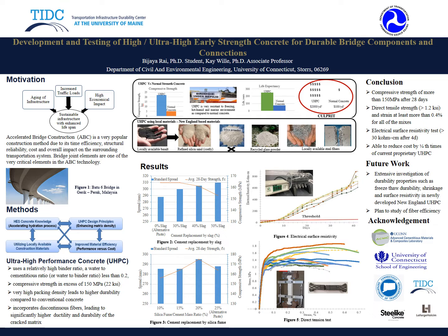Let's talk about the electrical resistivity first. It is the graph of preliminary results of electrical surface resistivity over the age of UHPC. The threshold limit for low permeable concrete has been plotted here in the red line. After 4 days, UHPC surpasses the threshold of 27 kilo ohm centimeter and continues increasing the resistivity until reaching a measurement of 1000, which reaches the detection limit of the equipment. This means that the pore structure is indeed extremely densified with aging of the concrete, and this is the key property for long-lasting durability of the material.